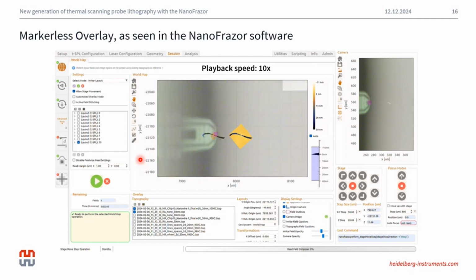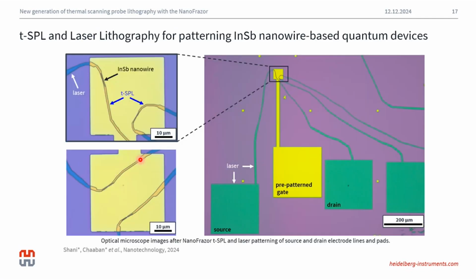Using this technique, we were able to create much more complicated nanowire devices in a simple manner. You can see an example of this here with the writing of transistors on top of indium antimonide nanowires. In this case, we used a hybrid lithography technique, combining the capability of the laser writer head to write the source and drain contacts, and then the TSPL tip to write the very high resolution contacts on top of the nanowire. If you look at the scales, you'll see that the laser writer was used to write 250 by 250 micron contact pads, and the electrode fan fans out over 1 millimeter in area.